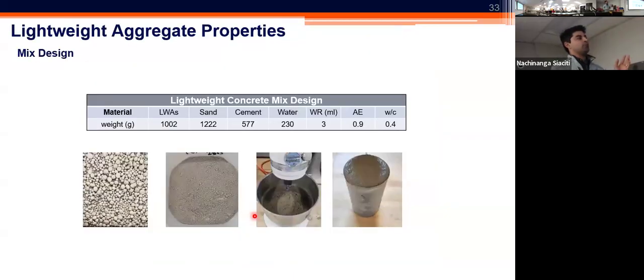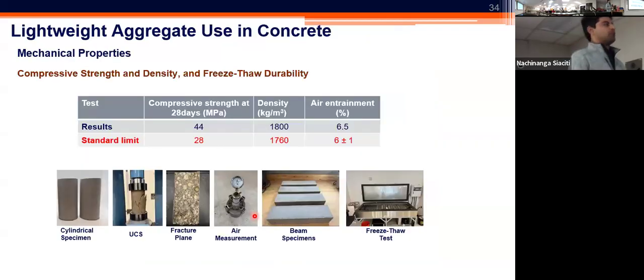So what we did was to document the characteristics of this aggregate and then incorporate them in the matrix of the concrete and then proceed with evaluation of the concrete characteristics. We did this by coming up with a basic mix design for the concrete, added the aggregates, and then came up with these cylinders. After curing, we proceeded with the testing of the compressive strength of these cylinders. There are existing ASTM standards that require us to hit the minimum of 28 megapascal at the 28 days for this structural lightweight concrete. We did achieve 44 MPa using the tailing-based aggregate.